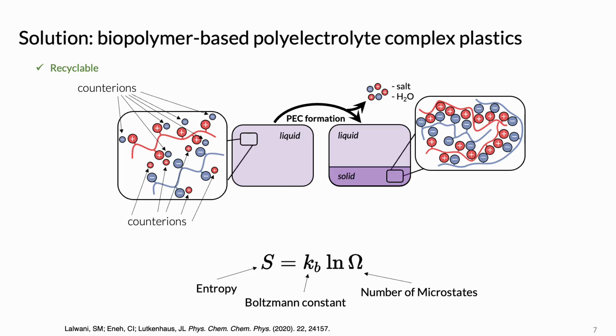And there are many more counterions per one polyelectrolyte due to the number needed to keep each polyelectrolyte neutral. So when these counterions are released, each of those increases the effective number of molecules in the system and thus the number of microstates. So thermodynamically, it's favorable to release these counterions so that we get to a higher entropy state, and this results in the polyelectrolytes collapsing onto each other and forming a solid phase out of the liquid.